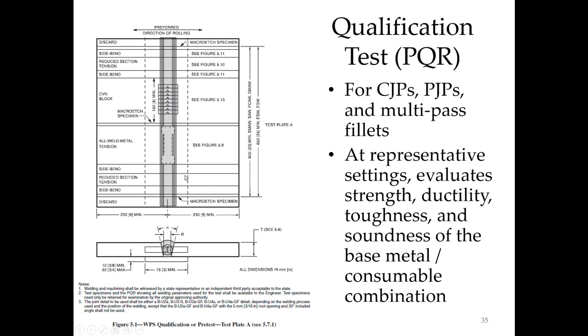We do conduct a tension test that tests right through the weld. But another important characteristic of weld metal is that it's based on those combinations that I showed you before. It's stronger than the base metal. So when you take a specimen out of this plate and you break it, you'll find that the base metal is always the thing that fails. So you get a very good representation of the weld metal in the qualification of your procedure, and not necessarily exactly how the weld will work with those joints, but that has to do with why the code gives you standard joints.